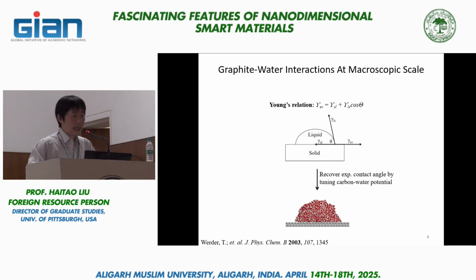The so-called contact angle, this theta angle, can be seen as a result of force balance between three surface tensions: the solid-liquid surface tension, the solid-vapor surface tension, and the liquid-vapor surface tension. You can just do a force balancing, and that will give you the Young-Dupré relationship, very widely used in analyzing the wetting behavior on pretty much all conventional